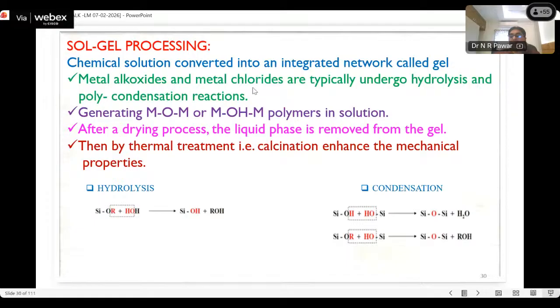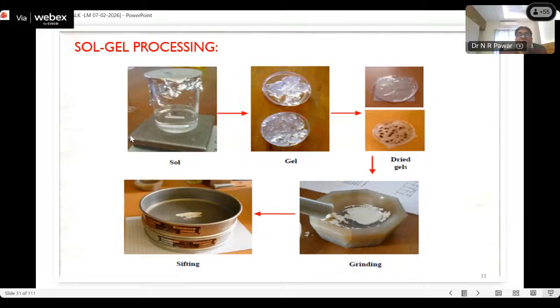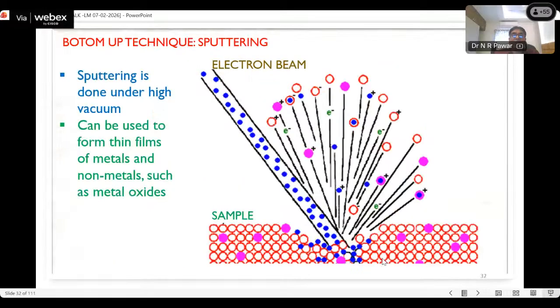Metal alkoxides and metal chlorides typically undergo hydrolysis and polycondensation reactions, generating bonds like this, metal-oxygen-metal or metal-hydroxide-metal polymers in solution, and we form the gel. After the drying process, the liquid phase is removed from the gel, and then thermal treatment, that is calcination, enhances the mechanical properties. Like that we have synthesized a number of nanoparticles by using this sol-gel synthesis. The sol is converted into gel, then it is dried, and after that sieving and grinding. This is a very simple technique.